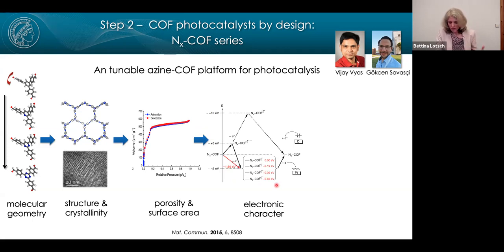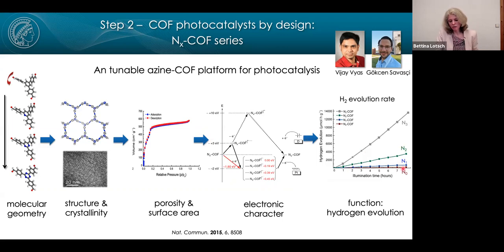And so, the bottom line is that for these systems, as we introduce nitrogen into the ring, we see an increase in the hydrogen evolution efficiency by a factor of 4 for each nitrogen that we add to the ring. And so that really reassured us that we can use the tunability of COFs at the molecular level to really tune the photocatalytic activity in these systems.